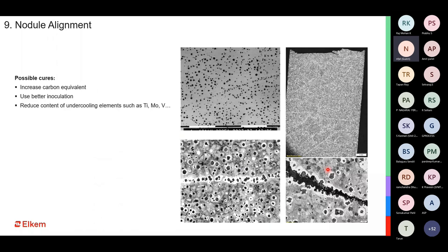Nodule alignment, again, this is related to undercooling in the case of ductile iron. In the case of gray iron, we have seen type D and E microstructure. Why does it happen? Because you have a lot of dendrites growing, and thereby the graphite flakes form on the sides of it. In the case of ductile iron also, when you have too much undercooling happening, then you have a lot of dendritic arms growing, and then you see this graphite precipitating towards the side of it, and thereby you get a nodule alignment kind of structure.